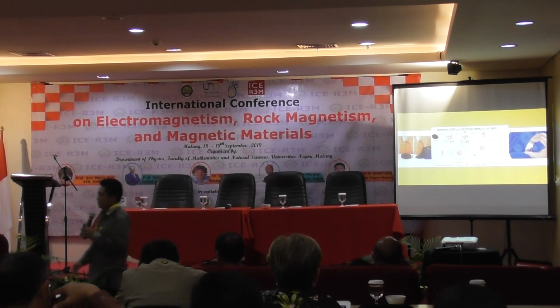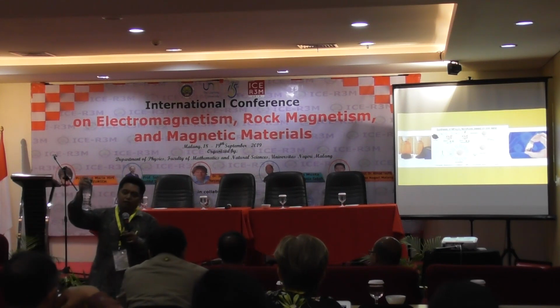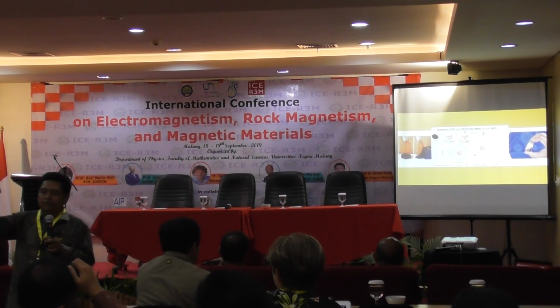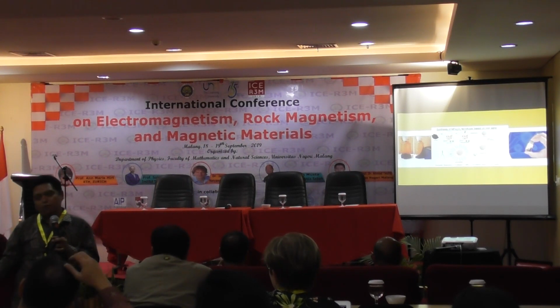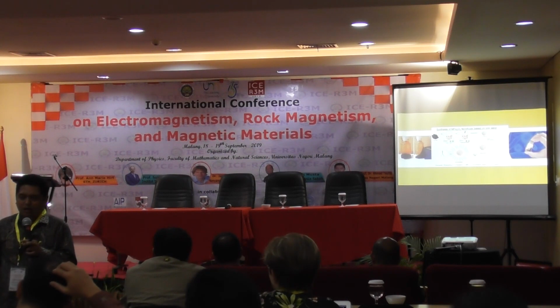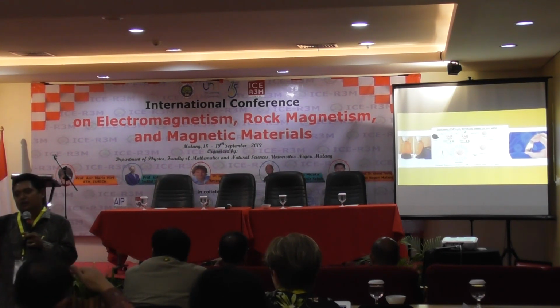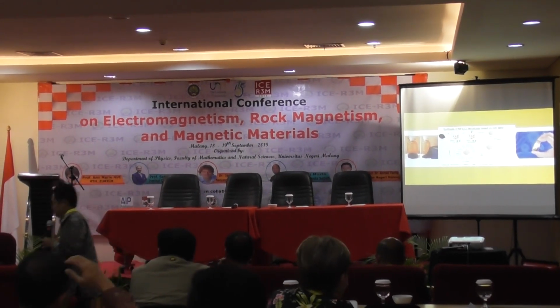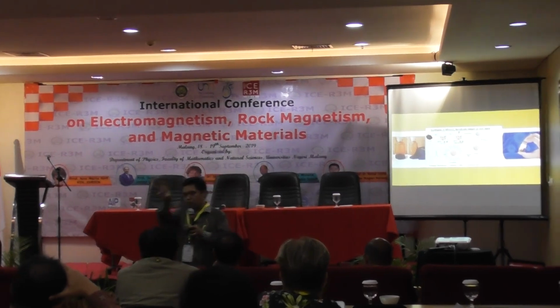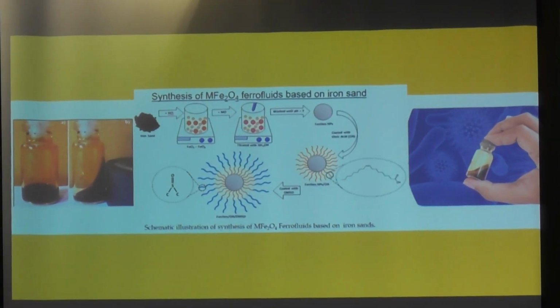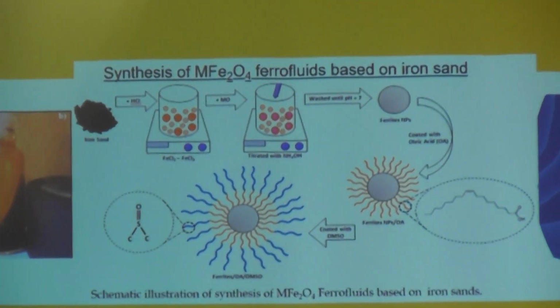Okay? The next section, if we would like to produce magnetic fluid, something like this, if we mix nanoparticles of big particle size, it is impossible to produce magnetic fluid. So we should make the magnetic nanoparticle, the ferrite nanoparticle, with very small size and high homogeneity and high purity. So we can disperse it in water, in alcohol, or another liquid carrier to produce the magnetics in liquid phase, something like this. So we need something like a surfactant. If we have already produced the magnetic nanoparticle, the next step to produce magnetic fluid is to cover the surface of the magnetic particle to prevent agglomeration.